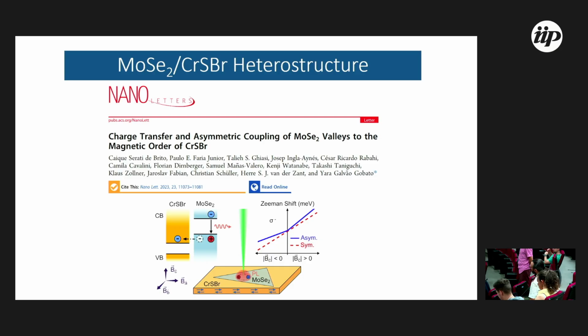But the exciton can probe the magnon not because of the energies. It's because of this hybridization that is sensitive to whether it's ferromagnetic or antiferromagnetic. And this can change because you have this spin canting effect. Right, but for instance, if your binding energy is super close to the conduction band, you would barely be able to resolve the excitonic peaks. Yes. And here it's very isolated, so you can resolve many peaks. So I was just wondering if this is solely a character of 2D materials, with the wave function extending perhaps through the vacuum. I think this effect in this case is specific, not for all 2D materials. It's only for this material. Okay. Because of this property it has.